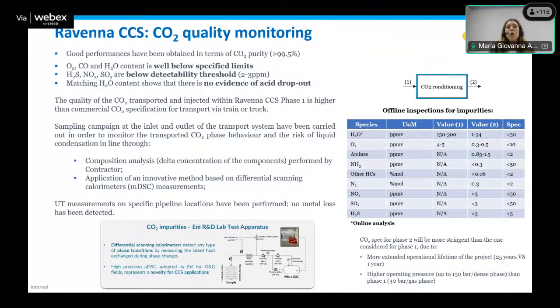impurities and also to specifically verify the CO2 phase behavior, and to verify that there were no CO2 condensation or water condensation phenomena that could potentially bring to water dropout and potentially also to the dropout of acid species. This was done through the application of a method developed in the Research and Development Department of ENI, based on differential scanning calorimetry, and we have seen that with these water contents, we didn't have any condensation phenomena.